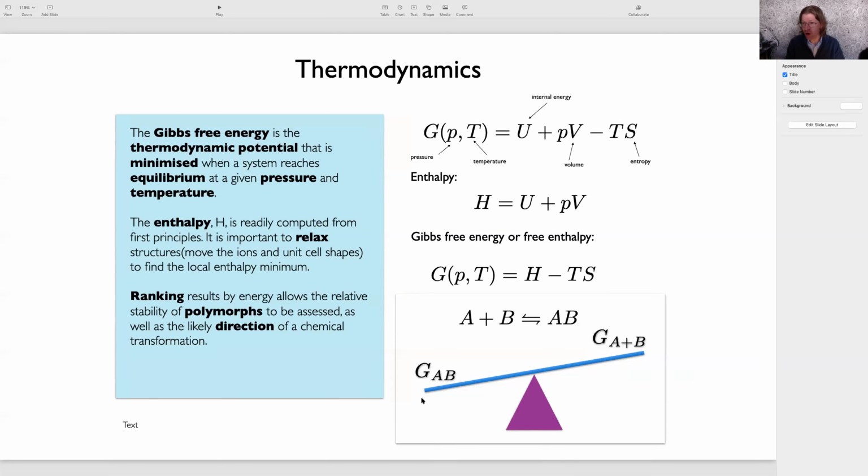Not because the experiments are wrong, but because they've been maybe interpreted slightly incorrectly and atoms have been put slightly in the wrong place. This particularly applies if you have hydrogen atoms in your system, because hydrogen atoms are light atoms. It somewhat shocked me to discover that for all these crystal structures I was downloading from databases, when they contained hydrogen, very rarely were they actually being experimentally measured in the positions that the crystal structure had them.